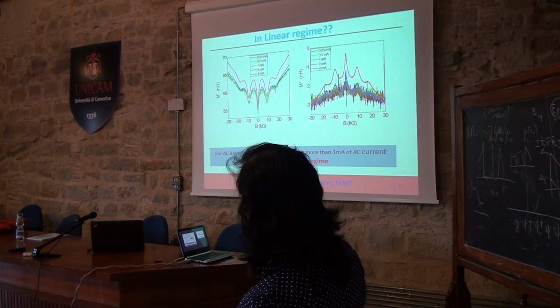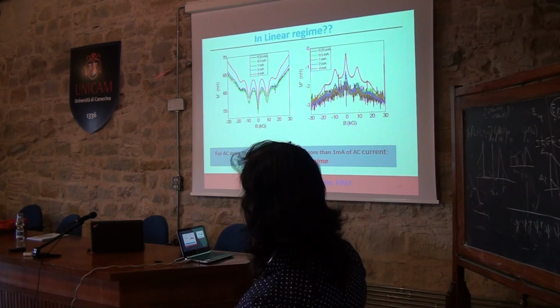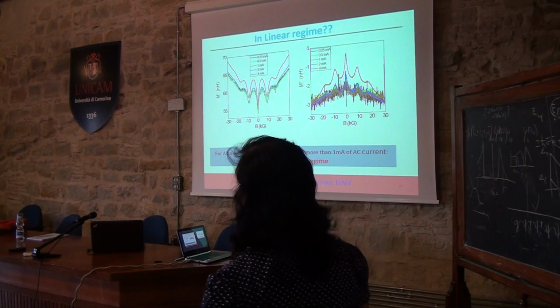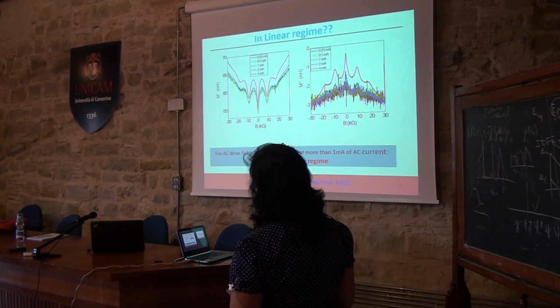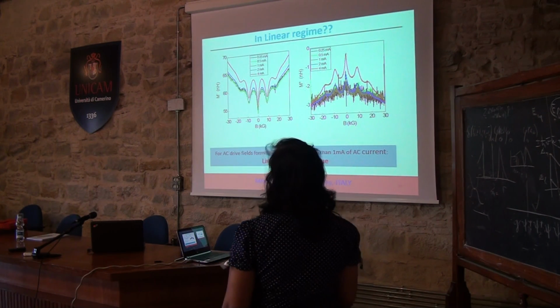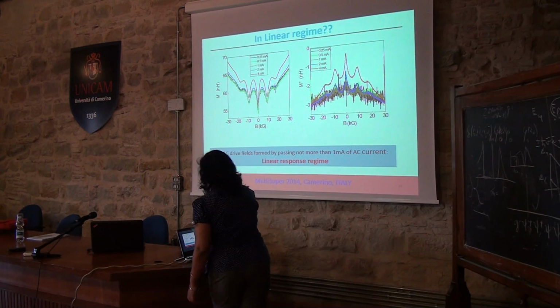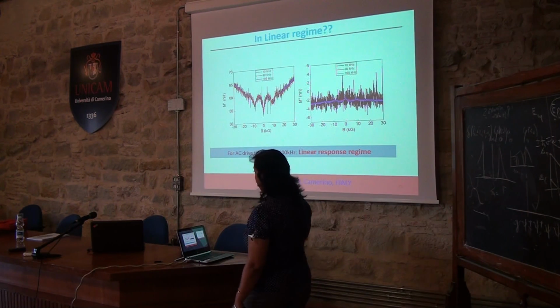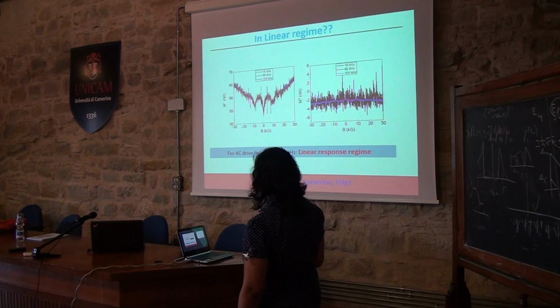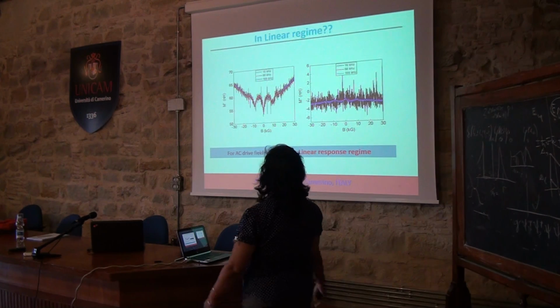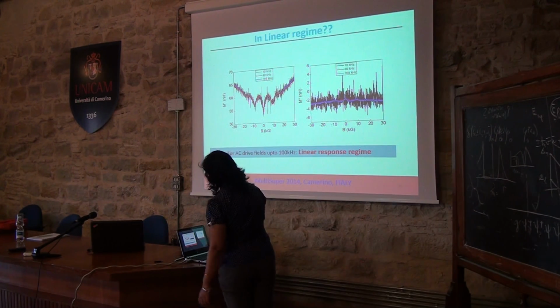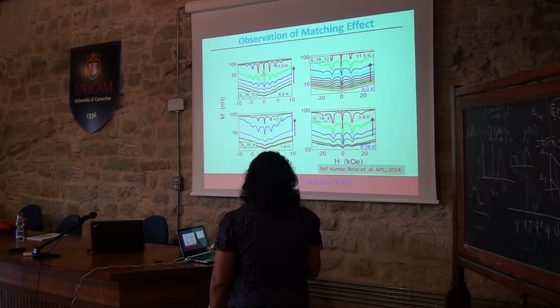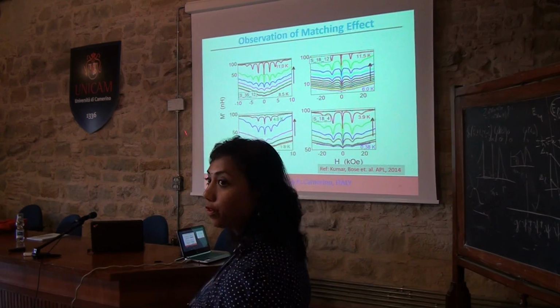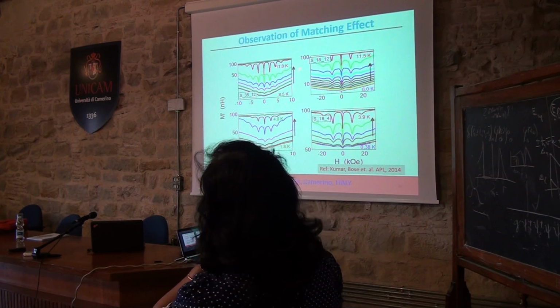So we checked whether we are in the linear response regime, and what we saw is that when you increase the current beyond, say, 4 milliampere, you start getting additional effects. So we try to measure always at very low currents so that we are always in the linear response regime. Similarly with the frequency dependence, we try to keep the frequency of the AC drive at 60 kHz, which was again in the linear response. So now is the result for the matching effect for all our samples. So you see these oscillations.